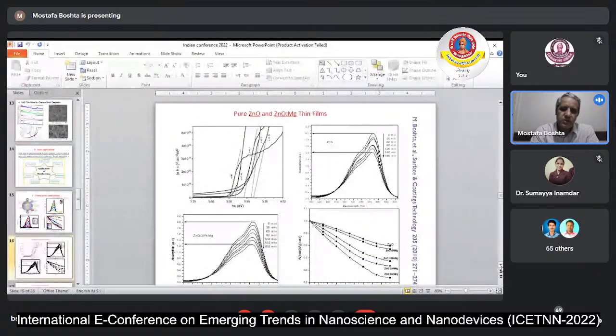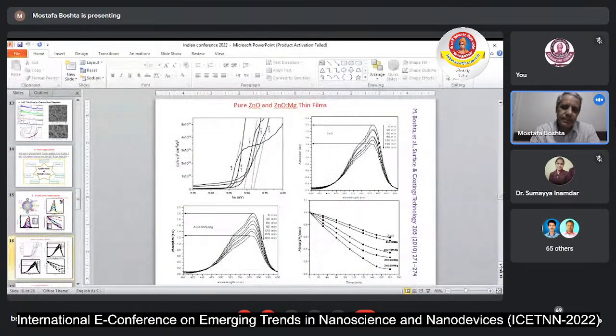Also, we use zinc oxide and zinc oxide doped magnesium, because all people are looking for another alternative material for the titanium oxide in the application of the photocatalyst. So the people suggested that zinc oxide is one of these materials, but we need to improve the quality and also improve the performance of the zinc oxide. So we added the magnesium oxide to the zinc oxide to move the energy band gap a little bit to the UV direction and make it a little bit wider band gap, which can absorb more UV light and also give us some improvement in the quality.